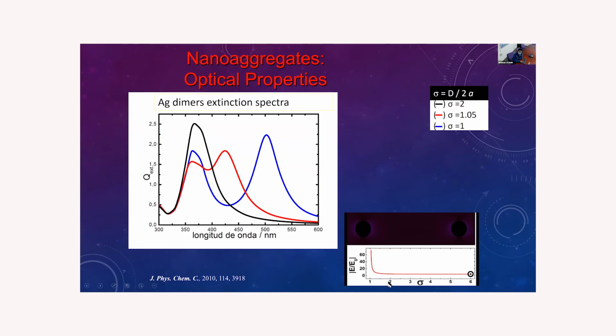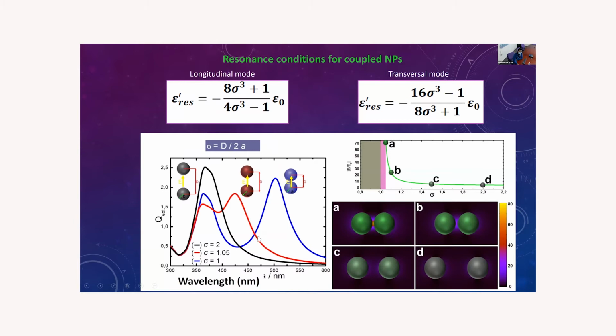So, luckily, in the next slide I will explain why they will start to see some signals when the nanoparticles are very close. At the same time, you are having some changes in the far field spectra. You will have a dramatic change in the region between nanoparticles. That means the hot spots, where initially you don't have any enhanced field between the nanoparticles, but at this point, and also at this, the electric field is as high as 70 times the incident field. So 70 times the incident field is a very enhanced field.